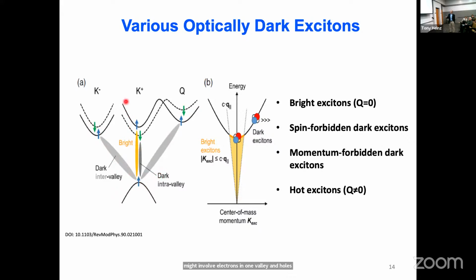It turns out there are also these spin splittings, so you have spin-forbidden transitions that are also very weak or unobservable that you might not be able to see. And there's actually even another factor, which is for the optically allowed direct transitions. That is only if you're right at the bottom of a valley. So if you have an electron with a bit more kinetic energy, then its kinetic energy is too high, or you'd say the exciton is moving along too fast and it can't disappear and transfer that momentum to a photon. So there are actually a lot of different types of dark excitations in these systems.